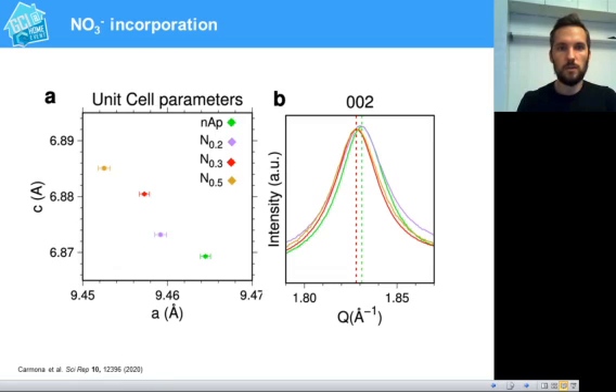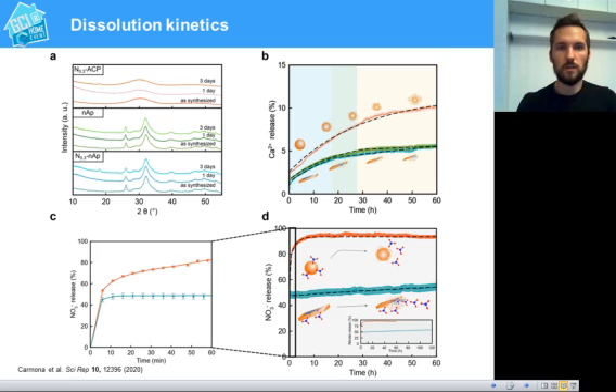However, nitrate enters the crystal structure of apatite in a way similar to that of carbonate. So disentangling the two contributions from nitrate and carbonate substitution within the apatite and quantifying it is not easy at this stage. But further hints of the effective nitrate incorporation can be obtained by analyzing the chemical stability and dissolution kinetics of these materials. We put these materials, the amorphous and the nanocrystalline, in water suspensions, and we measured the calcium release and nitrate release.